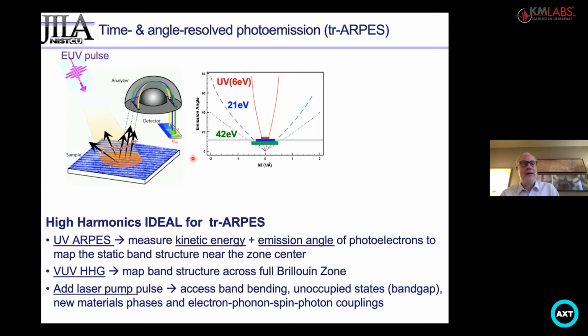And that means that for angle resolved photoemission, if you want to get a full picture of the valence band structure of a material, the ideal energy of the photon is 10 eV to 40 electron volts, which is generally the range where the best ARPES is done. If you have very long wavelength light, like ultraviolet photons from a conventional laser, you may be able to get photoemission, but only for photoelectrons that were traveling pretty much in the direction toward the surface to begin with. So you only get a partial view of the band structure of the material.